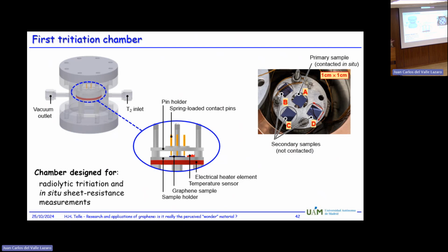The way we did that, and because you have no way in a closed chamber like that to actually look at the system in real time, we placed 4 of the samples into this chamber. One was contacted to actually send, as I said early on, an electric current through it, and with increased hydrogenation, the resistance increases and the current slows down. And then some other samples for comparison to do other experiments with it.